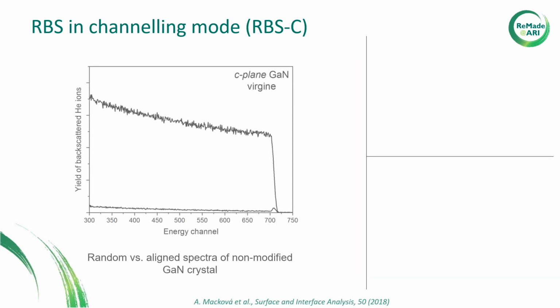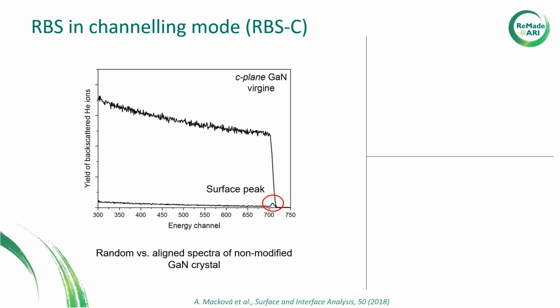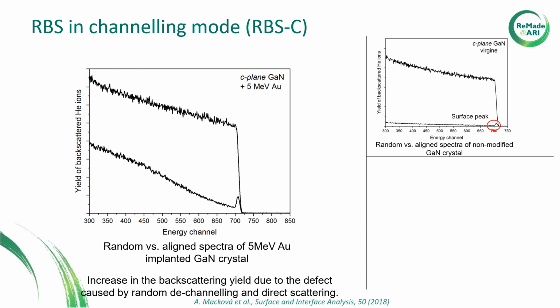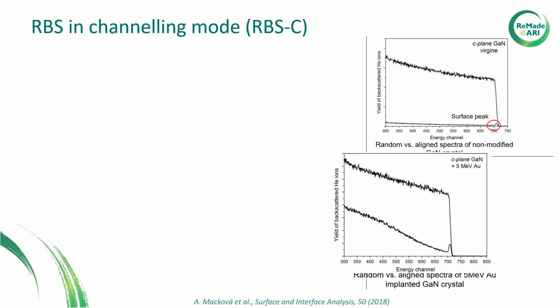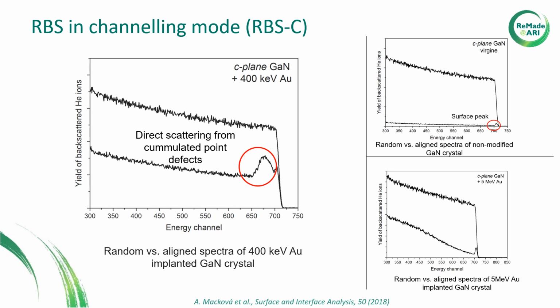The aligned spectra of perfect crystals typically exhibit low backscattered yield, which is just several percent of the backscattered yield captured in random direction. This is usually connected to the presence of native defects and random dechanneling. The aligned spectra exhibit a characteristic surface peak connected to backscattering on the first atomic layer, which shields underlying atoms. Crystal damage and lattice distortion will lead to increased random dechanneling, and the point defects and impurities lead to direct backscattering. The accumulation of point defects in a narrow subsurface area will result in the appearance of a dechanneling peak. From the analysis of the dechanneling peak, it is possible to determine the relative number of dislocated atoms and their depth distribution.